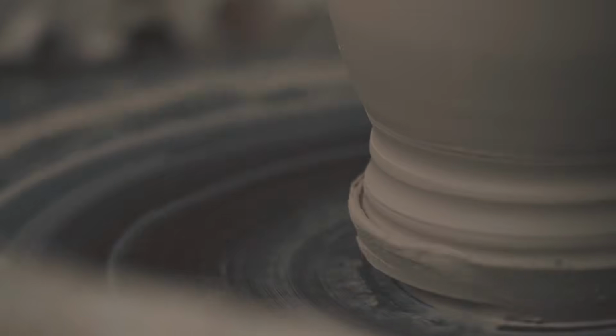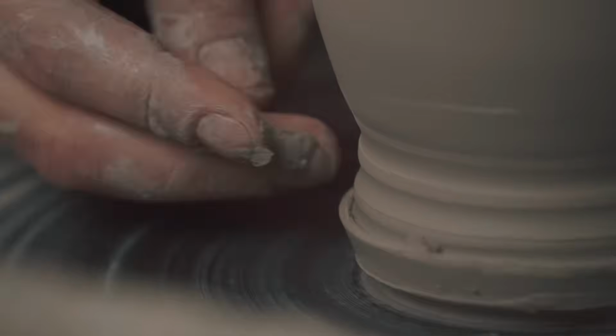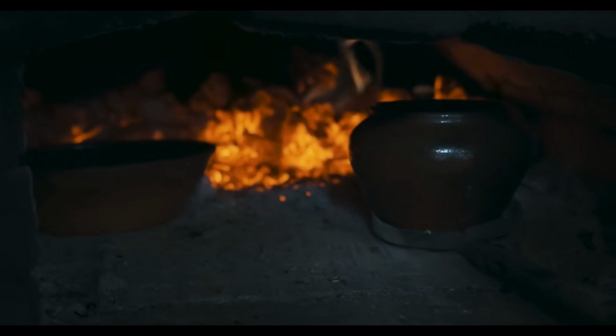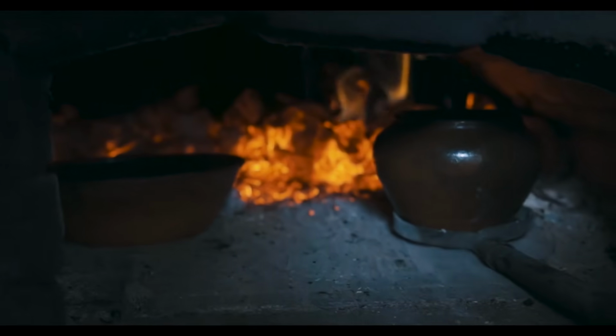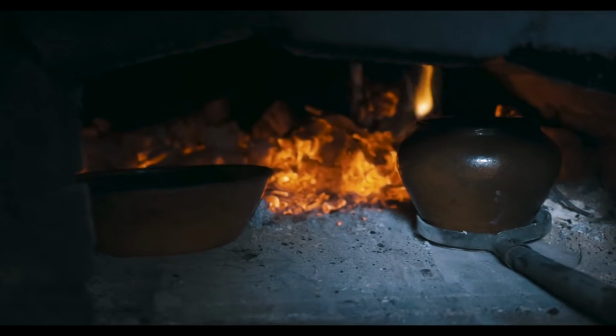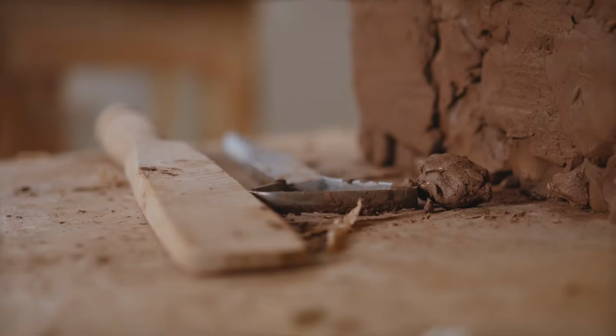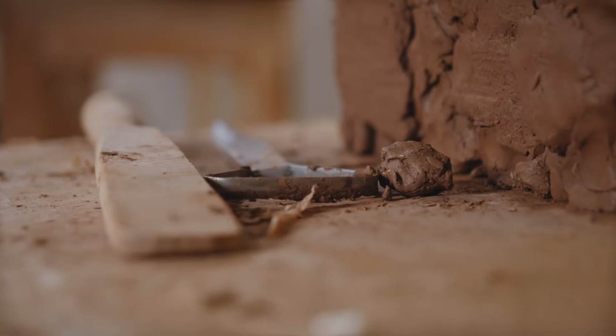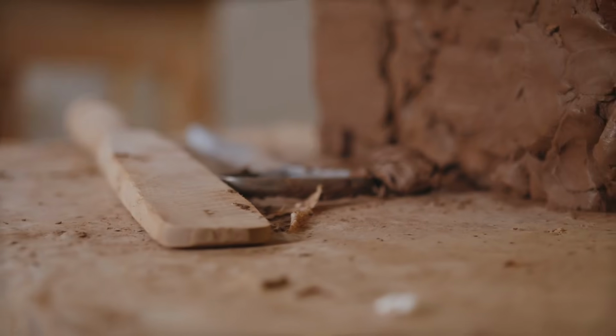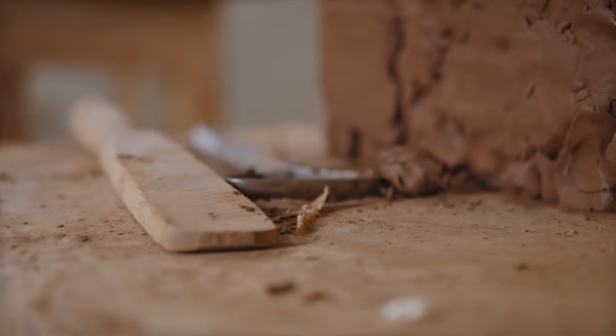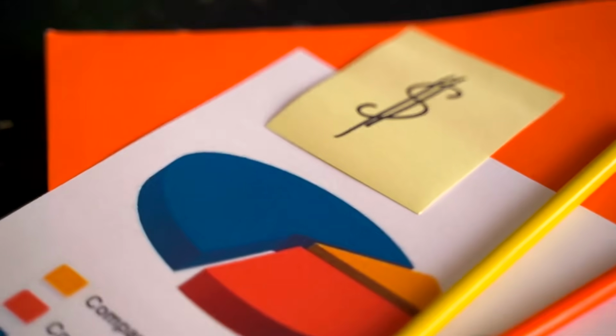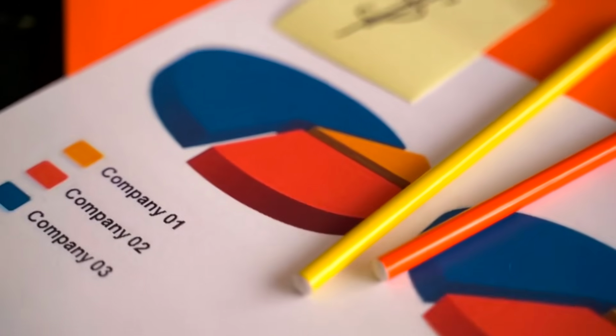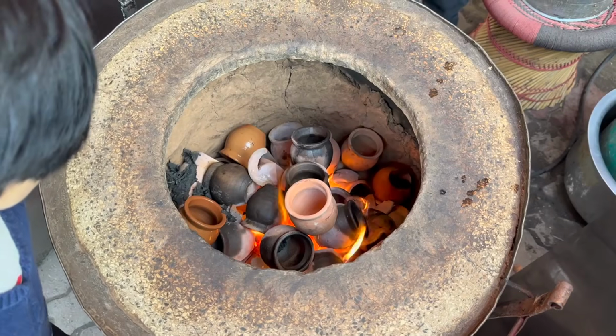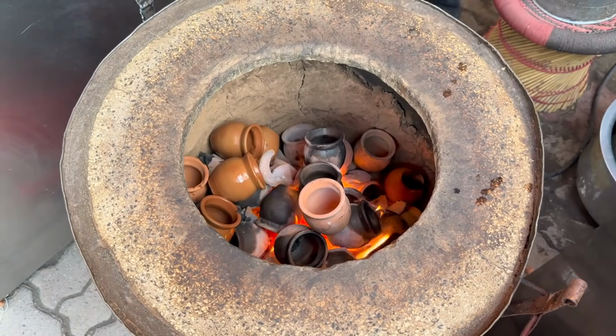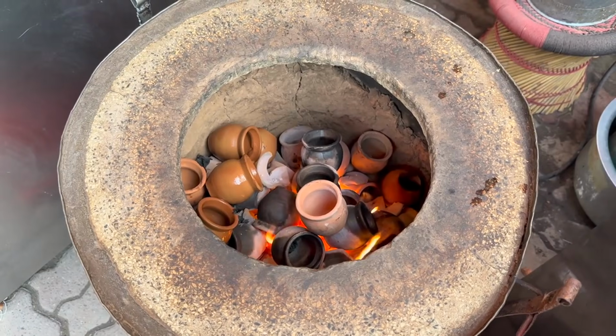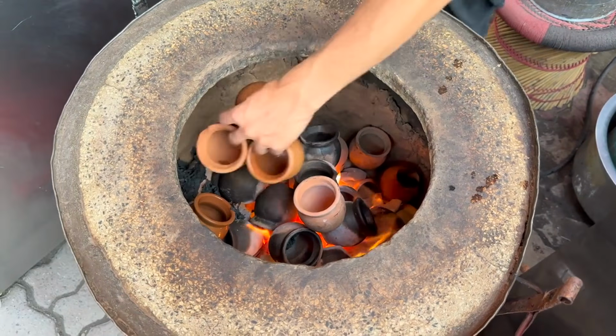The clay itself also contributes. Fired terracotta has a thermal conductivity of roughly 0.8 watts per meter Kelvin, compared to concrete's 1.6 to 2.0. So even the pot walls are conducting heat at half the rate of the surrounding concrete. And because the pots are hollow, the effective thermal mass of the roof is dramatically reduced. You've replaced dense, heat-storing concrete with air and low-density clay. The roof now has less capacity to absorb and hold heat. It charges slower in the morning, it discharges less in the evening, and the peak load that reaches your ceiling at 7 p.m. is a fraction of what a solid slab would deliver.